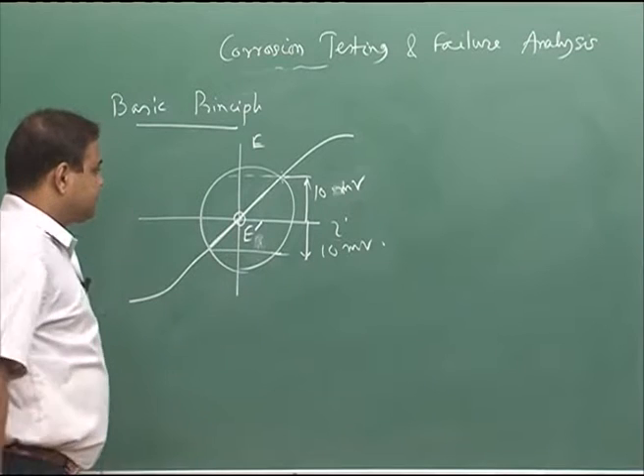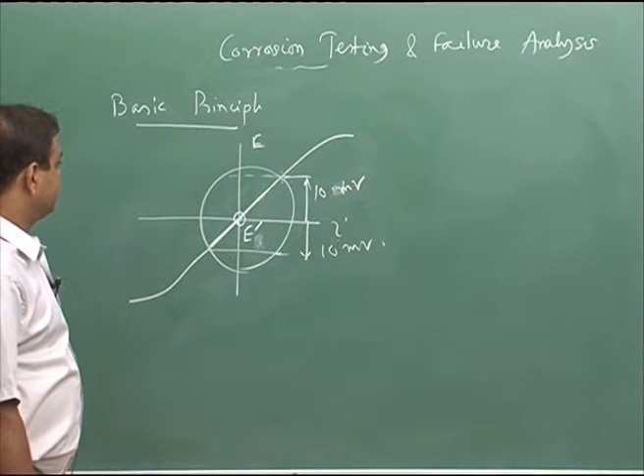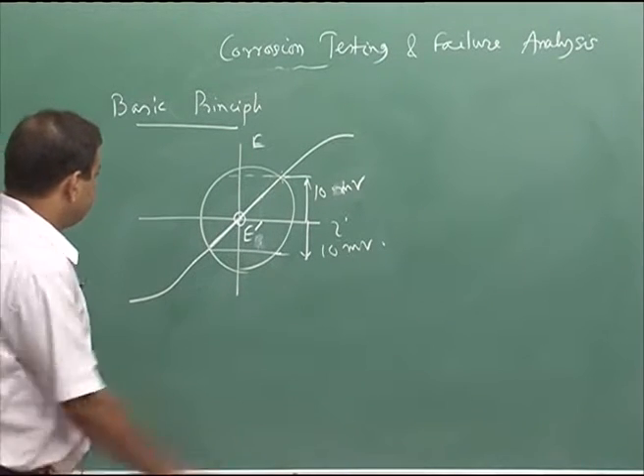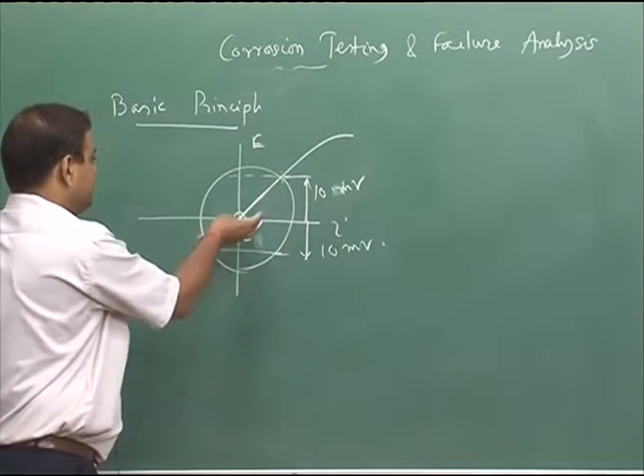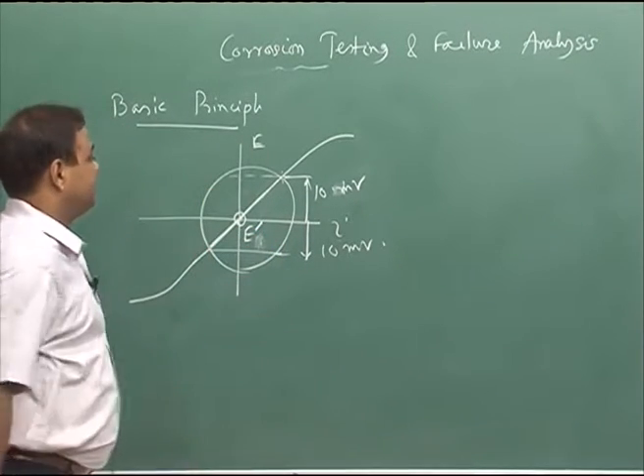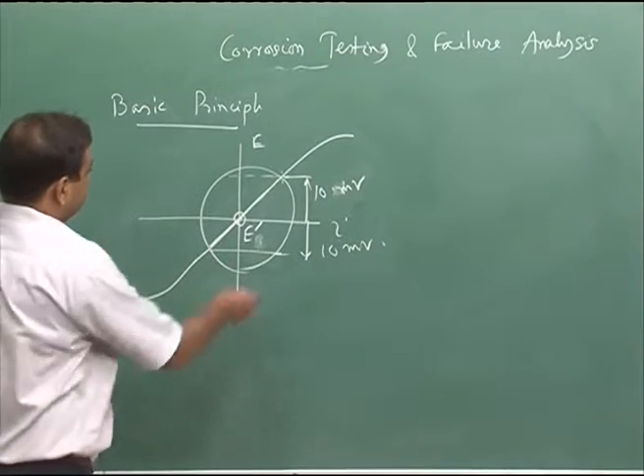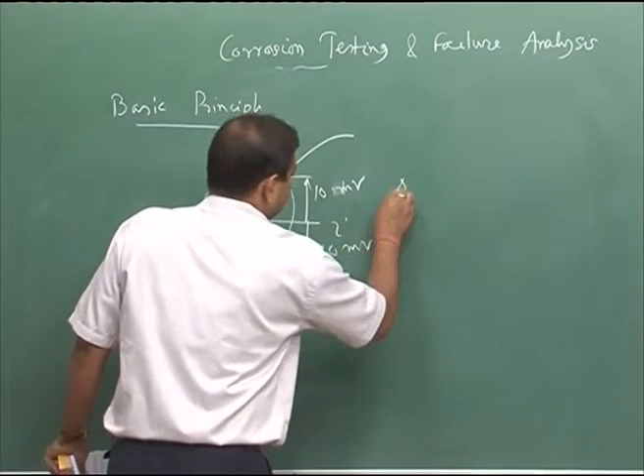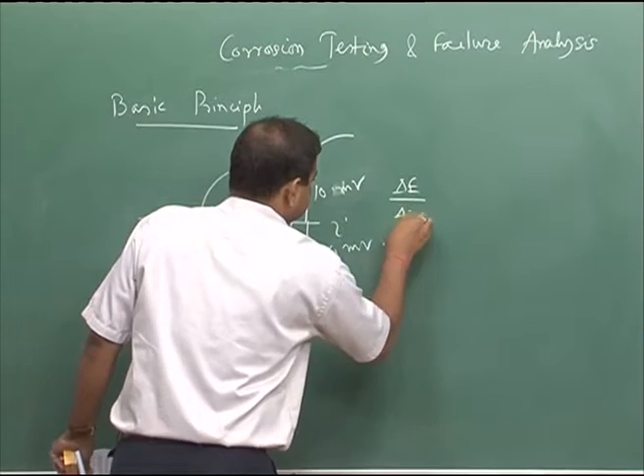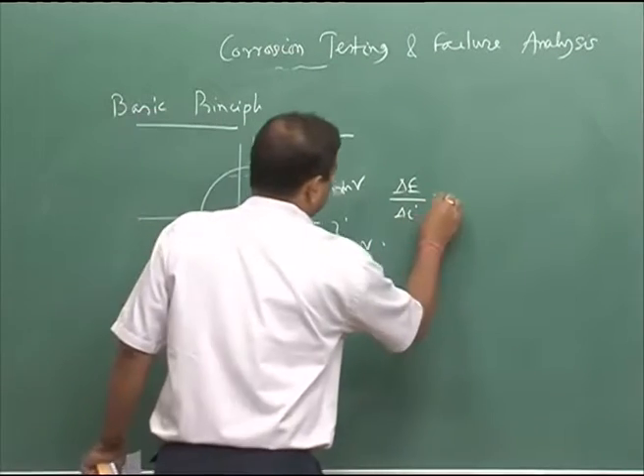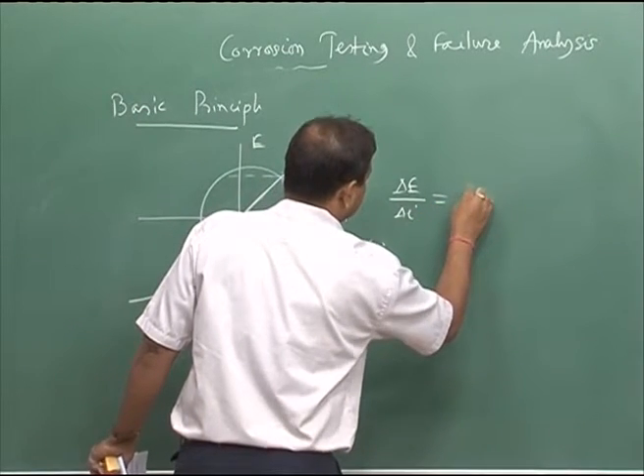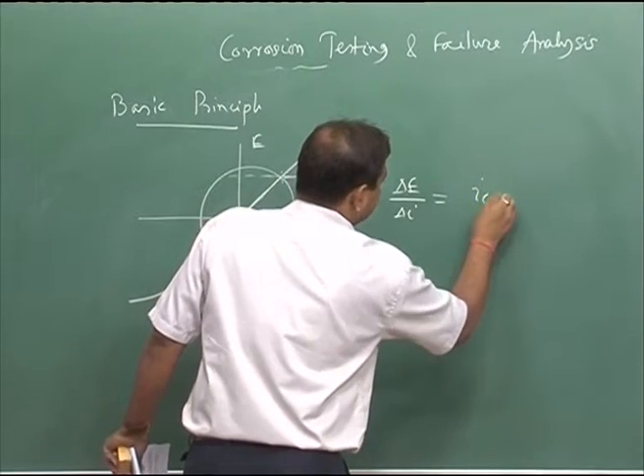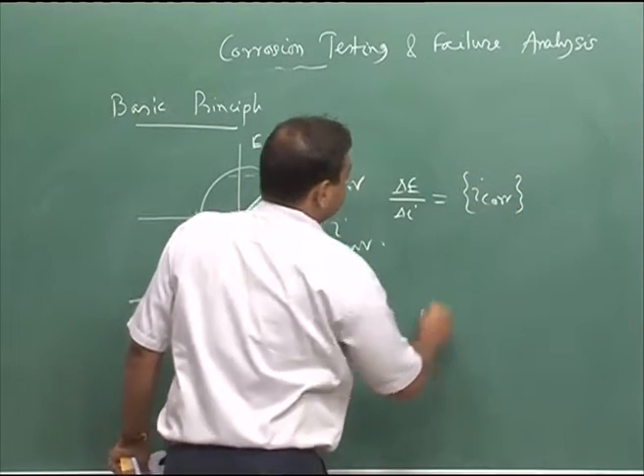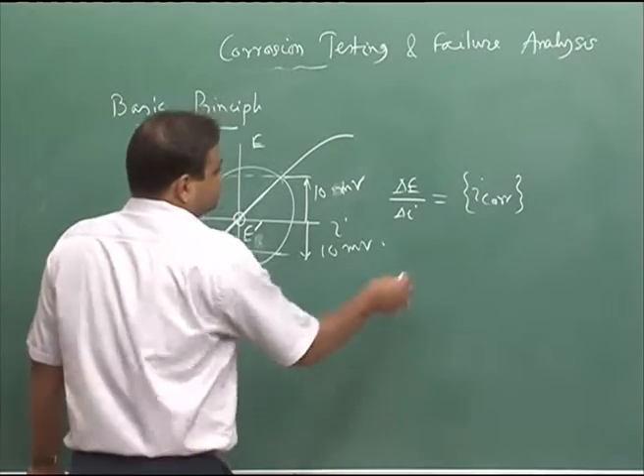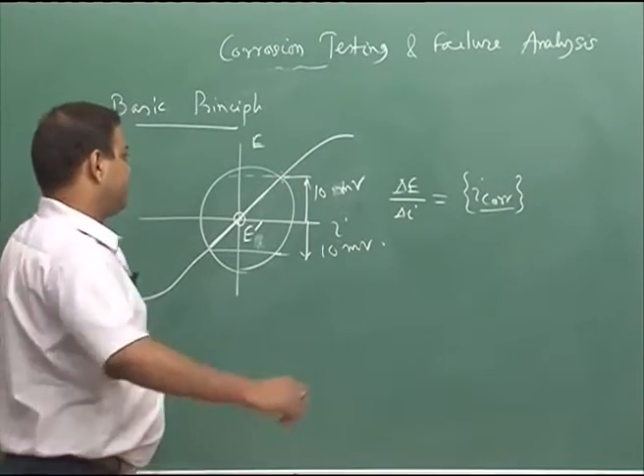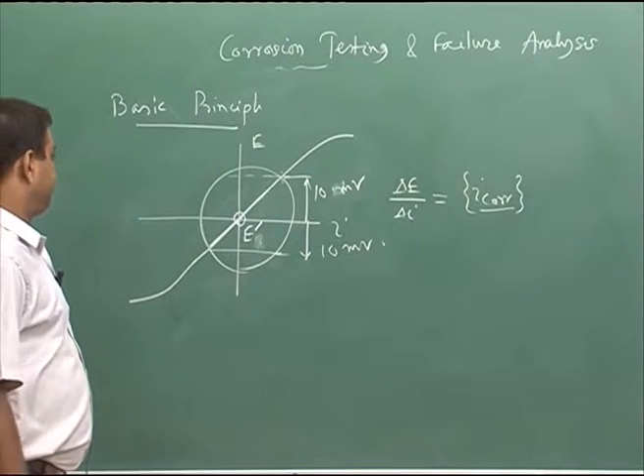Potential versus current density would be linear within that narrow range of 10 millivolt on the positive side as well as negative side, and the slope of this line, which is actually del E versus del I, would give information about I-corr. So once we know I-corr, we can find out what is the corrosion rate of that metal.